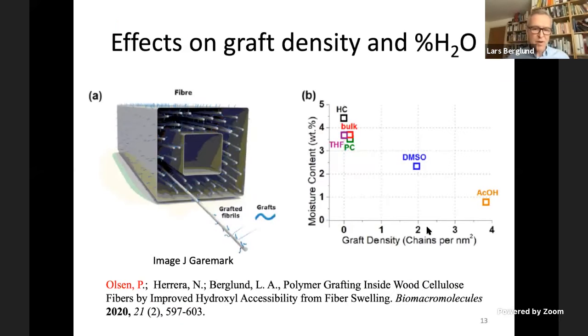So this is another example from a published paper. So if he measures graft density and relates that to moisture content, so moisture content here, if you have very high graft density as you get with the acetic acid procedure, and you compare it with the bulk procedure, the moisture content is much lower. So another effect that we obtained from this is that we lower the moisture absorption of our material by this fairly straightforward procedure. And actually, it really helps properties of thermoplastic composites as well. Because basically what happens if you do melt processing of these fibers, they will disintegrate and form nanofibers in the process.